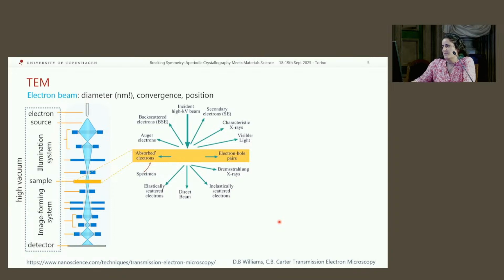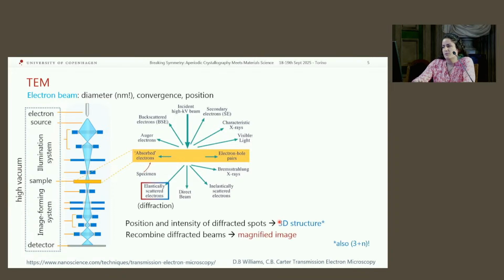We can look at some of them. So, for example, we can look at the elastically scattered electrons, which, if our sample has long-range order, the elastically scattered waves will interfere with each other, and this is what gives the diffraction pattern. So this is what we can use for crystallographic analysis. But because this instrument is actually a microscope, we have lenses after the sample, and we can even recombine these diffracted beams to form an image which is very magnified.